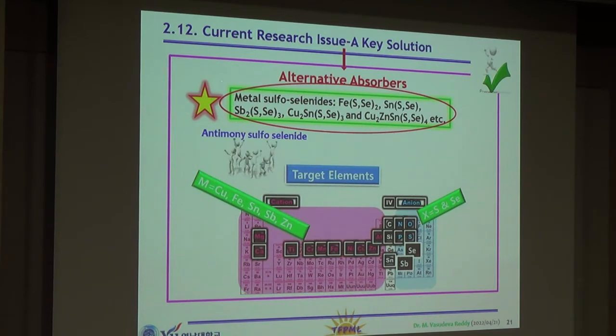Even though CZTS and copper tin sulfide or antimony or iron sulfide are promising, the problem with iron sulfide is there exist several secondary phases. Similarly, in case of copper tin sulfide or copper zinc tin sulfide also the same, there are several phases. It is difficult to form the single phase. And in case of tin monosulfide and selenide or antimony sulfide and selenide, there are less number of phases, and these are promising.